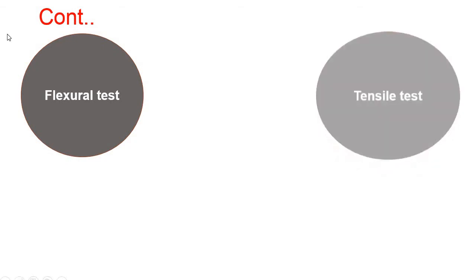As per the standard, we are going to take the specimen measurement, length into breadth into thickness, which is 125 mm into 12.5 mm into 3 mm, and the gauge length during the specimen was adopted as 100 mm. A load cell of 10 kilonewton was used. Normally we will take the rate of loading maybe 5 mm per minute, and then we will go for the tensile test.